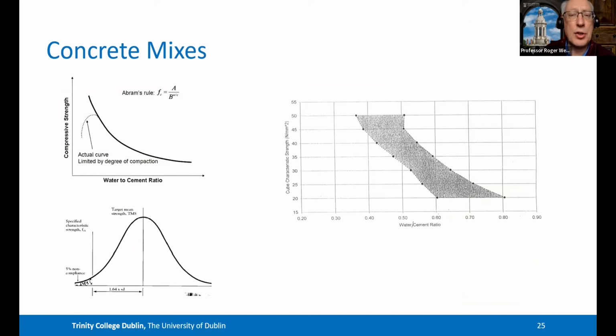In relation to moving on to the constituents of concrete, we watch very closely the water cement ratio, because that has a big influence on strength. It has a big influence on durability. But when Mark Richardson and myself, with the help of the ICF, did a study of almost all of the ready mix plants in the country, and we published that work, you can see in the graph on the right hand side that for a 40 megapascal concrete, there's a wide range of water cement ratios being used, and there are reasons for this. Quality control in terms of the target which you have to aim for, different available aggregates, some of which are stronger or weaker, and perhaps different cement sources as well. So there are reasons for this variability.